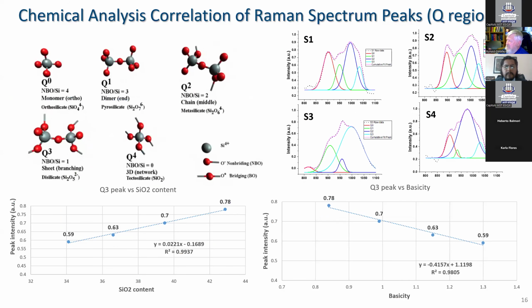The structure of slags, particularly silicate slags, is polymeric in nature, and the individual chain length of those silicates can actually impart a vibration that is detected by Raman that has a specific peak wavelength. When we extract the Raman spectra from this signal, we can deconvolute the peaks and represent the Q0 through Q4 structures in the silicate region of the Raman spectra and relate that directly to the structure. And ultimately that relates to the basicity, silica content, and even viscosity of the slag.